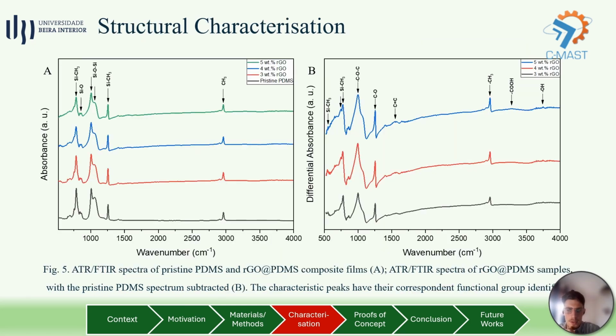In the structural characterization by ATR, all characteristic infrared peaks of both PDMS and rGO were observed, as you can see in the graph on the left, including the influence their interaction had on the peak's morphology, since the tendency was to lose intensity but gain width due to the loss of purity, but also the creation of new contact points, as you can see on the graph on the right.